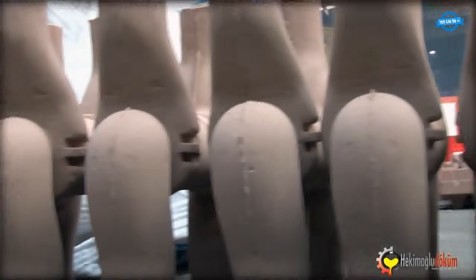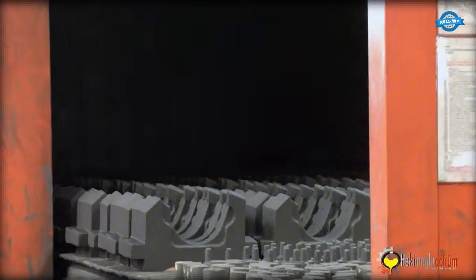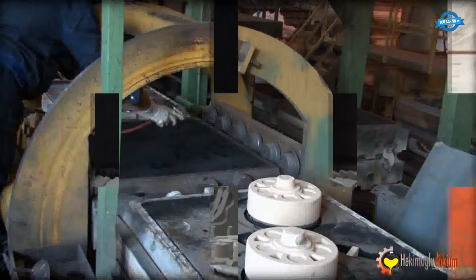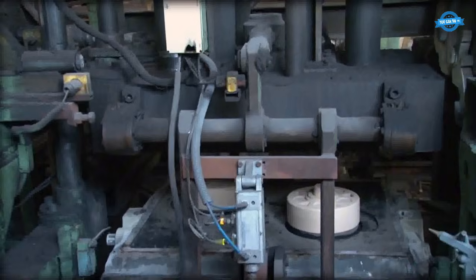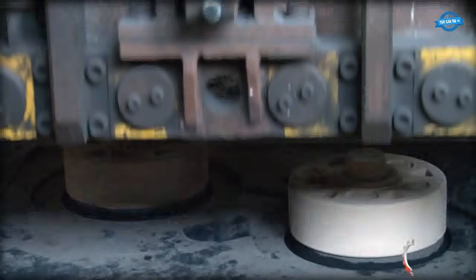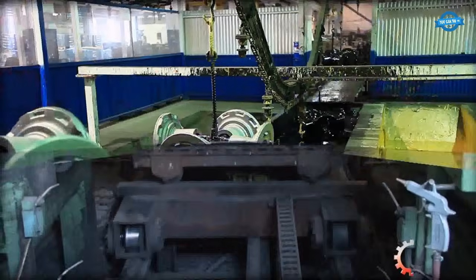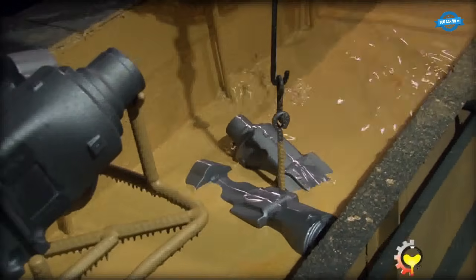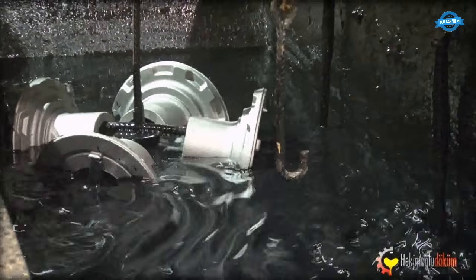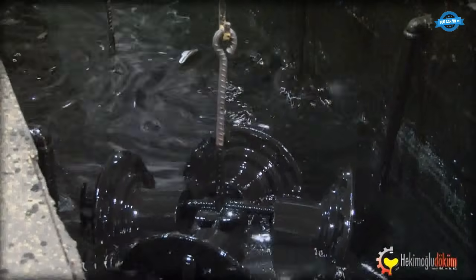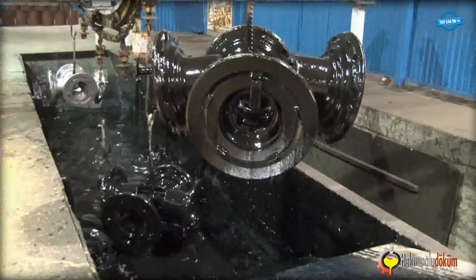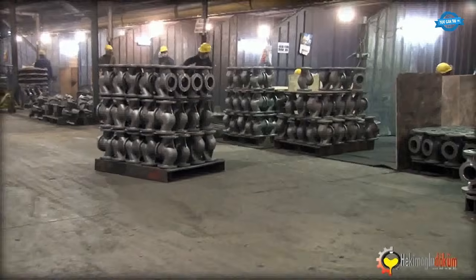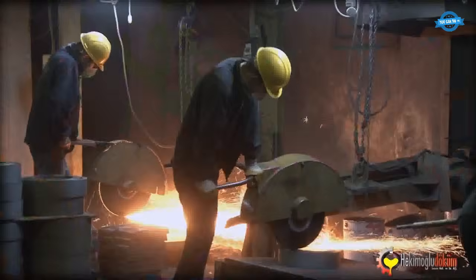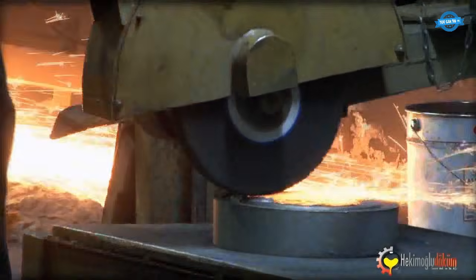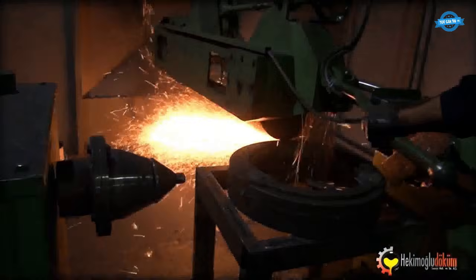Every batch has to arrive at exactly the right chemistry. Silicon, manganese, carbon, a few tenths of a percent off, and the finished hub either cracks under load or wears out 3 years early. Cores get made in specialized machines running the cold box and shell core methods in sizes from 25 to 60 liters. That is what shapes the internal cavities of the casting before any liquid metal shows up. Get the core wrong and the finished part looks perfectly normal from the outside, right up until the moment it doesn't.